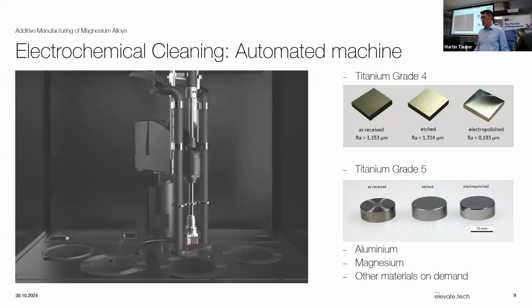I'm just wondering why or how after etching the Ra increased in thickness. It's not the thickness, it's the roughness. So the roughness increases a little bit, because etching was quite aggressive to take away the passivated surface, and then we had some pits, but these were removed again after the polishing. Thank you.